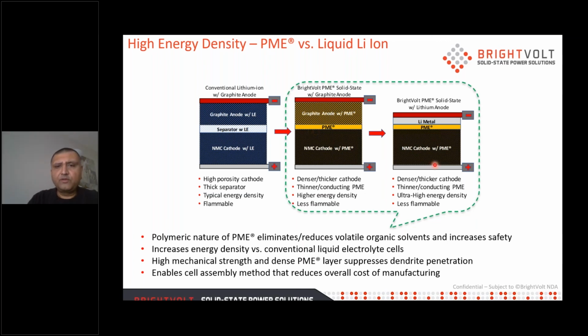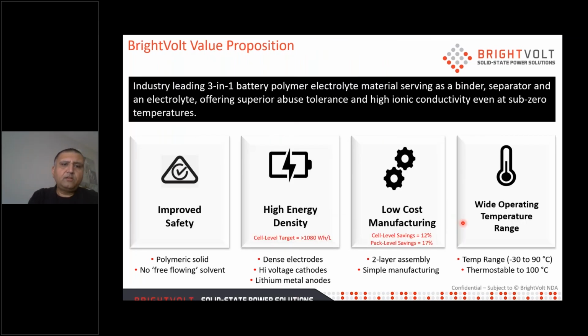And then, of course, moving from this more standard conventional cell design to some more novel materials such as lithium metal anodes or silicon graphite anodes gives you a further bump in energy density. And so when you look at the value proposition of a technology such as ours, it's really fourfold. One is that the technology can offer a very high level of safety, being extremely tolerant to electrical, mechanical, and thermal abuse. And that's in large part because there is no free-flowing solvent or liquid in the cell.